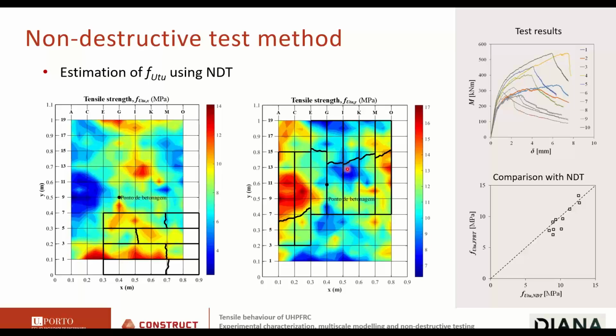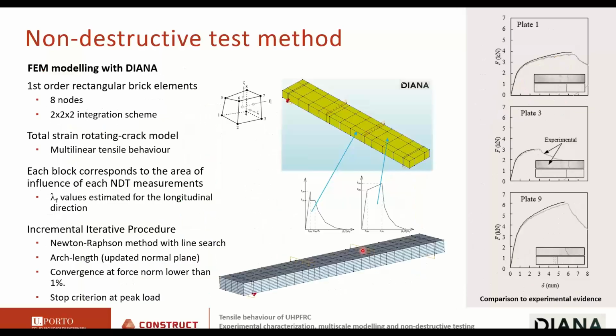Sometimes the agreement is not perfect because the roughness of the plate on the free surface side was such that the thickness was not really constant throughout the slab. This is the full range of results in the 4-point bending tests, and we did some inverse analysis. This is how the tensile strength from the test compares with the tensile strength estimated by NDT. And we can use Diana also.